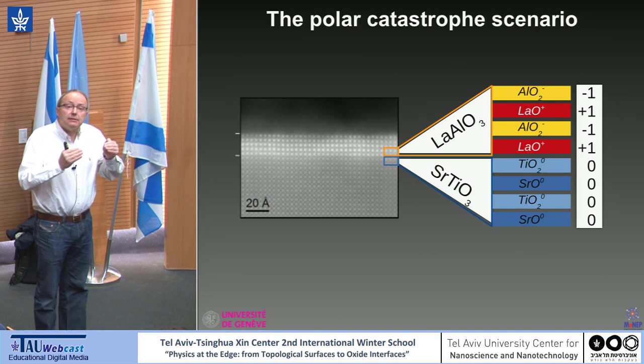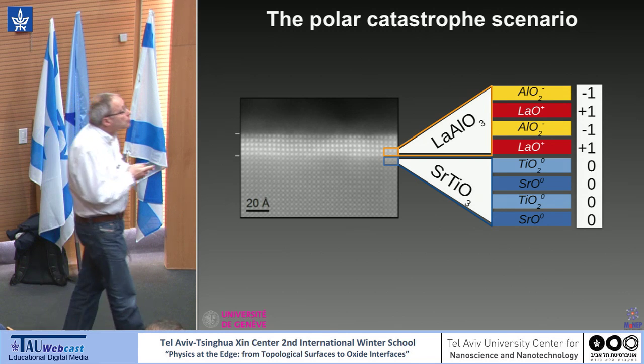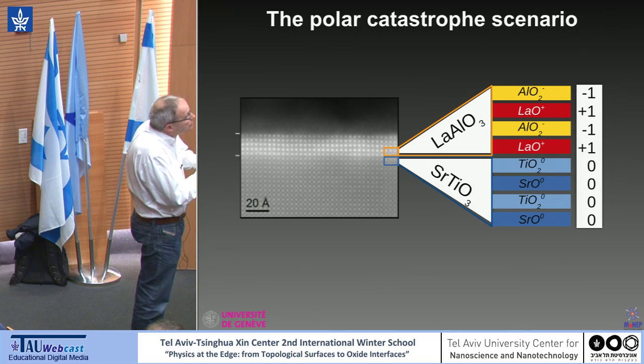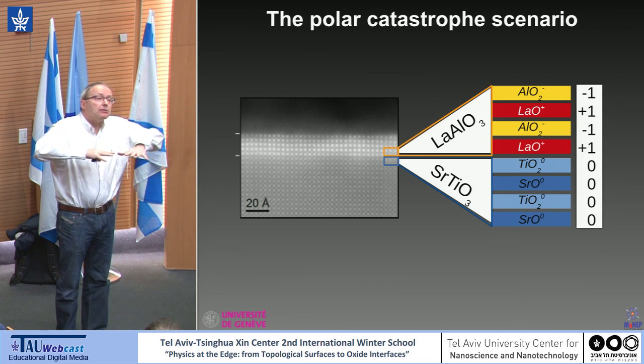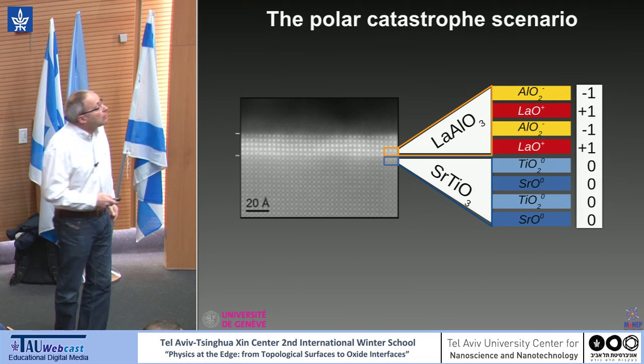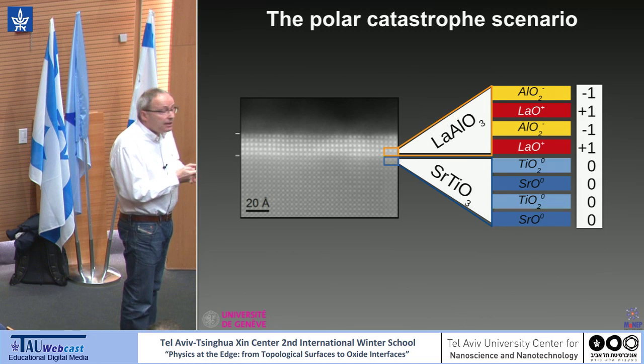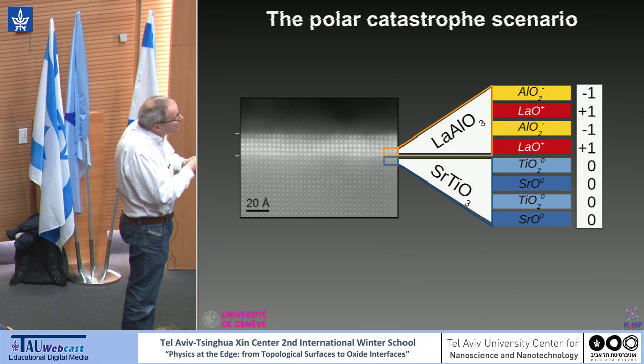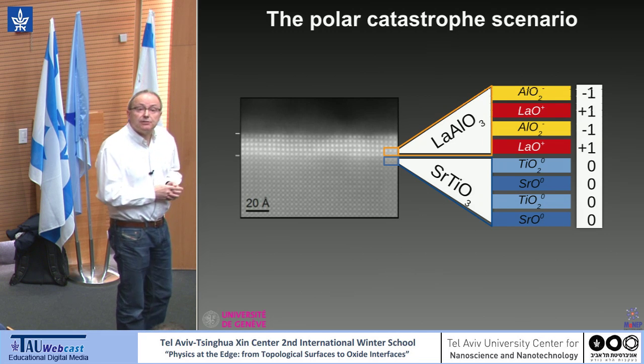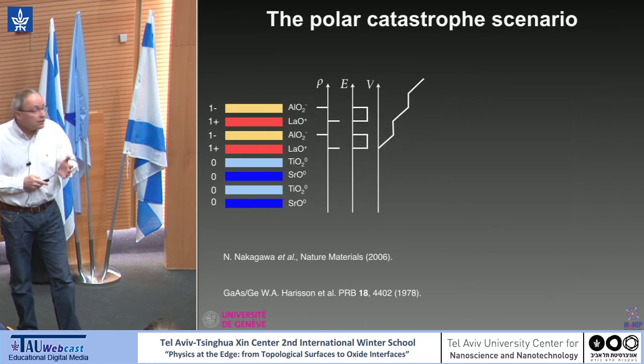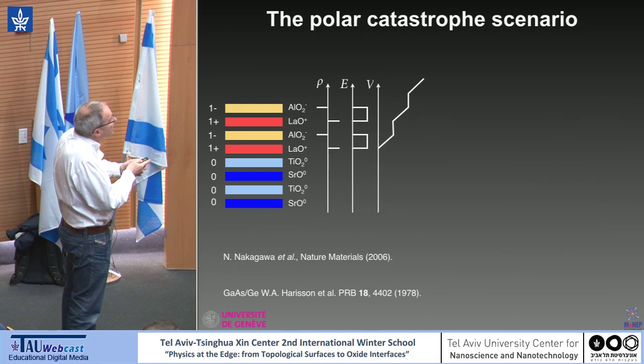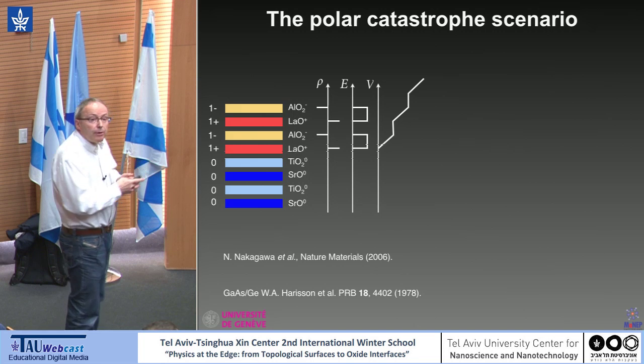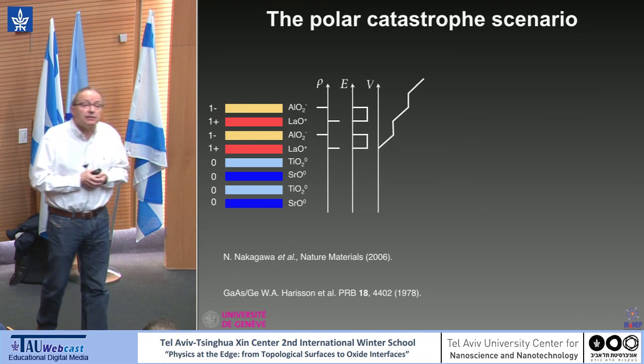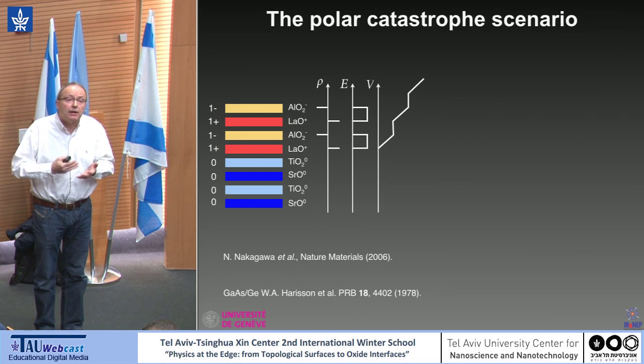But when you move to lanthanum aluminate, lanthanum is 3+, and so this plane has a formal charge, +1, -1, +1, -1. Now, if you think about infinite capacitors, you know that in an infinite capacitor, the electric field is confined between the planes. So what you have here is an electric field between this layer and this one, and an electric field between this layer and this one. Now, if you think in terms of potential, when you start growing your lanthanum aluminate layer, you have these electric fields I was mentioning, and you see that the potential is growing as you increase the thickness of the lanthanum aluminate. And this is this polar catastrophe.